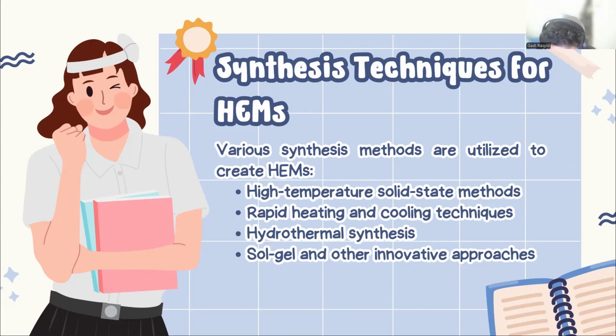Furthermore, the effective adjustment of reaction parameters and raw material ratios allows for the production of HEM with different structures and properties, thereby further expanding the range of HEM applications. Chang and colleagues successfully synthesized a series of high purity, high entropy oxides with spinel structure using hydrothermal synthesis. These HEOs maintain their crystalline framework and exhibited unchanged electrode reversibility due to the high entropy effect. Furthermore, the hydrothermally synthesized HEO show exceptionally high specific surface areas and extended cycling stability.